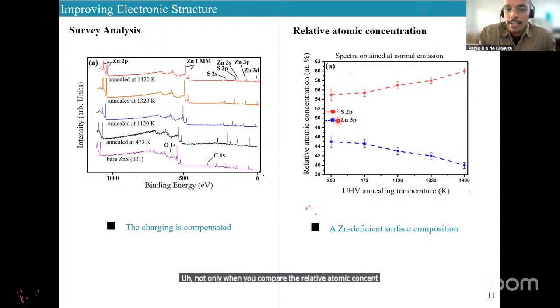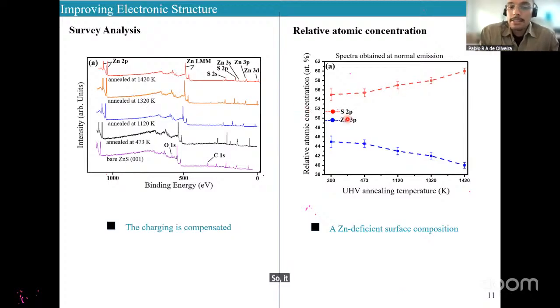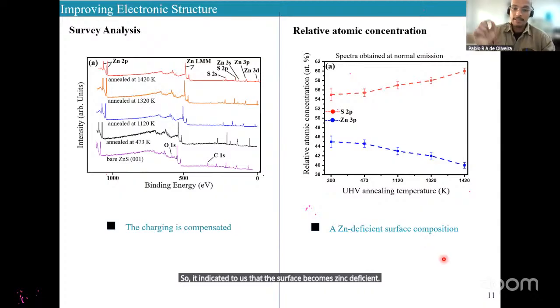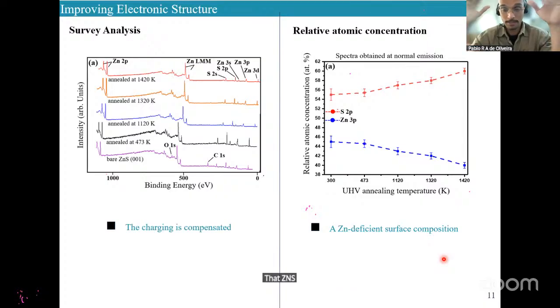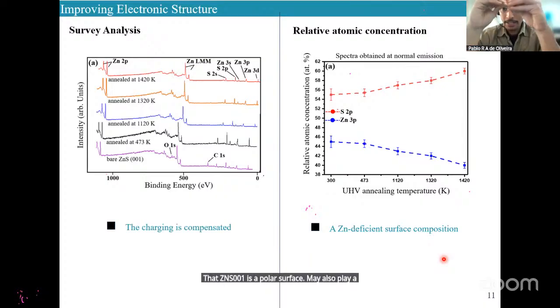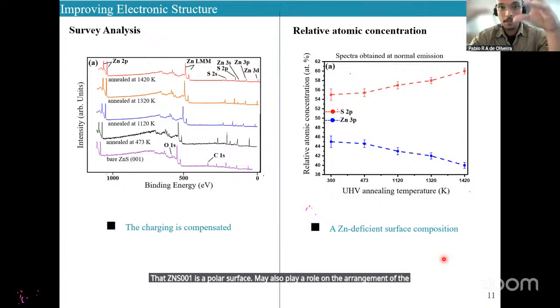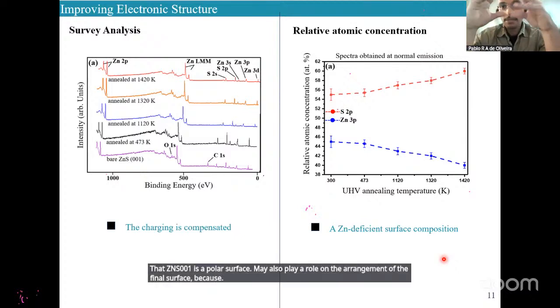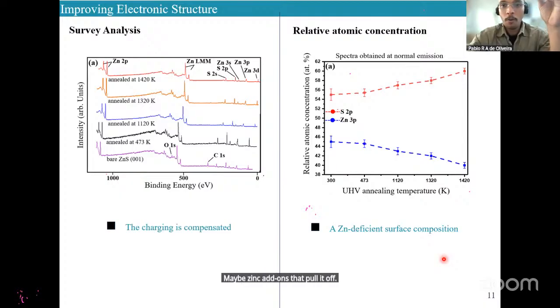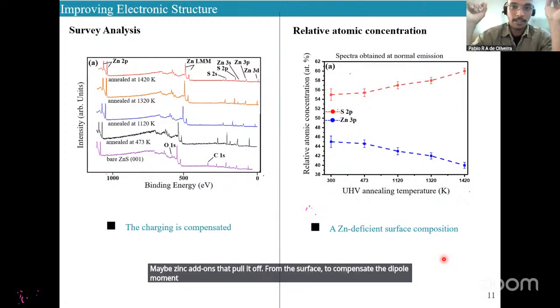Notably, when you compare the relative atomic concentration of sulfur and zinc 3p as a function of the annealing temperature, we note a decrease in the zinc content relative to the sulfur. So it indicates to us that the surface becomes zinc deficient. And this zinc deficiency, if you remember that ZNS001 is a polar surface, may also play a role in the arrangement of the final surface, because maybe zinc atoms are pulled off from the surface to compensate the dipole moment that you showed initially.